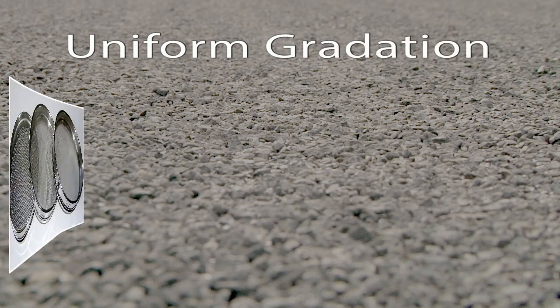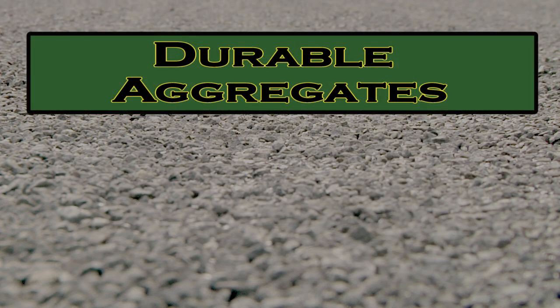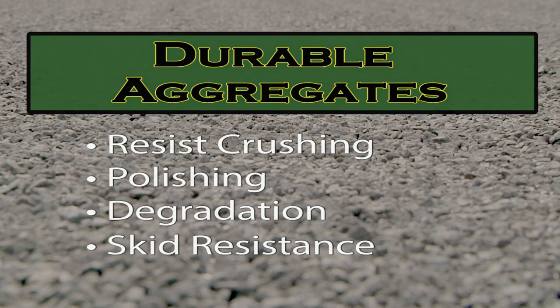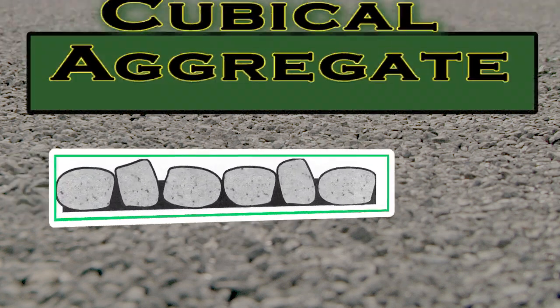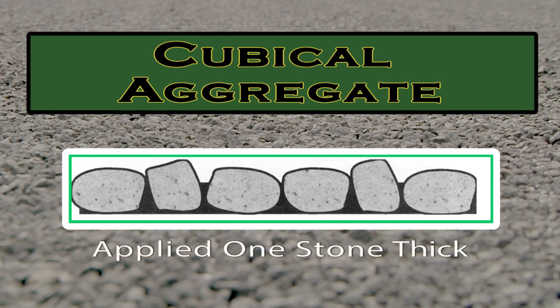Use a uniform gradation aggregate with less than 1% passing the number 200 sieve. Aggregate must be durable to resist crushing, polishing, degradation, and have good skid resistance. Aggregate must be cubical for better interlock and be applied as a monolayer, meaning 1 stone thick.